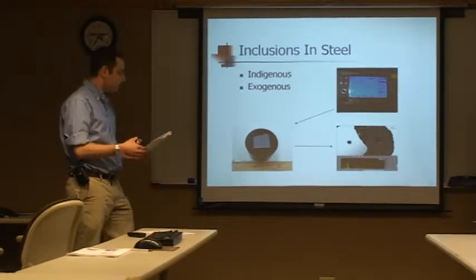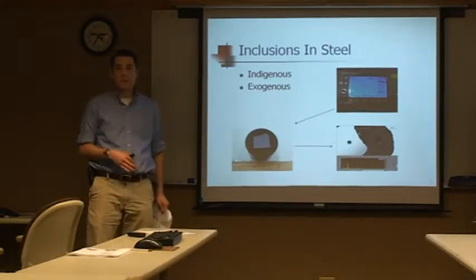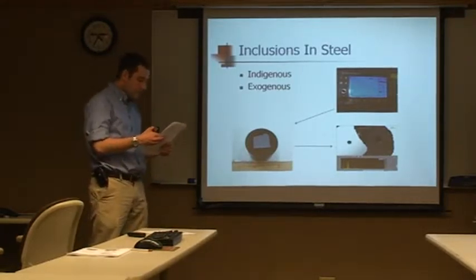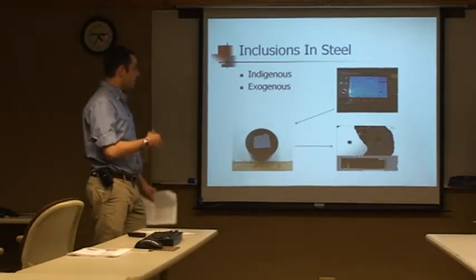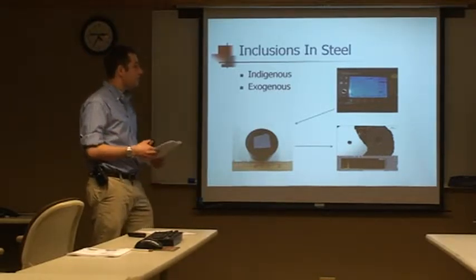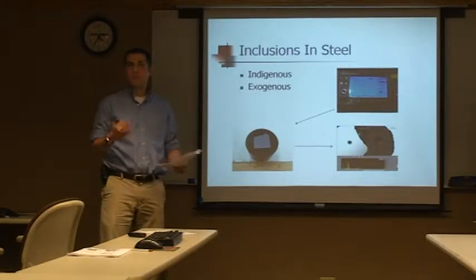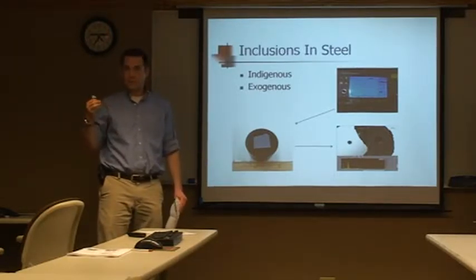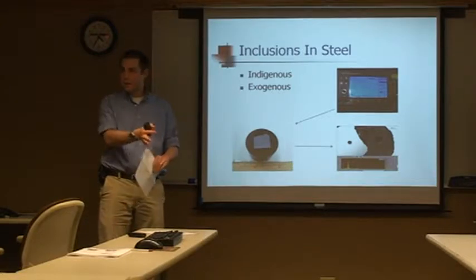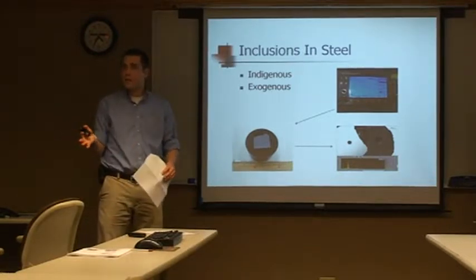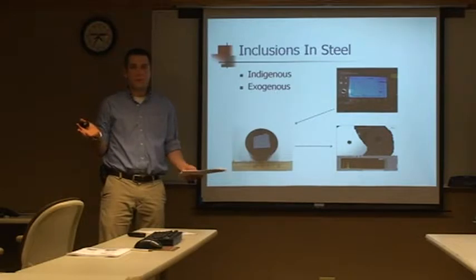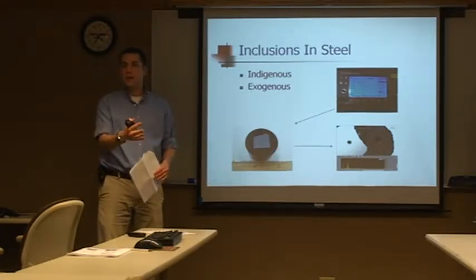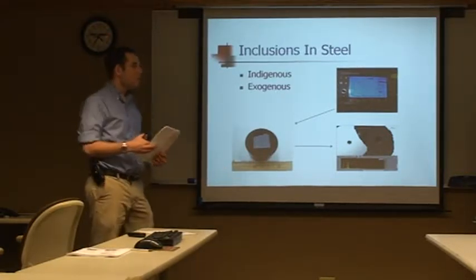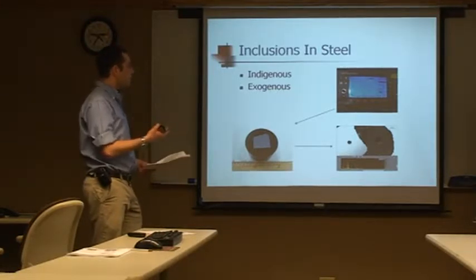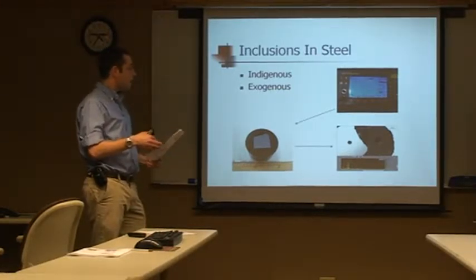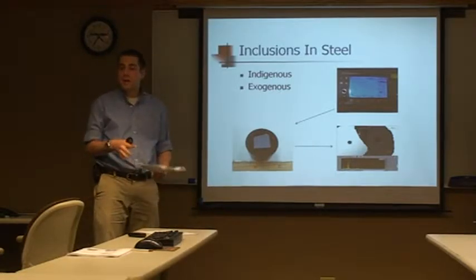As I said before, we take all sorts of precautions to keep our steel as clean as possible. But when you think about it, we're dealing with a liquid that's 3,000 degrees Fahrenheit. If you think of how a river can erode a bed and cut through a mountainside over time, imagine if that river was 3,000 degrees. It would erode things away at a much faster rate. So we have all sorts of things in place to keep any exogenous inclusions small and as infrequent as possible.